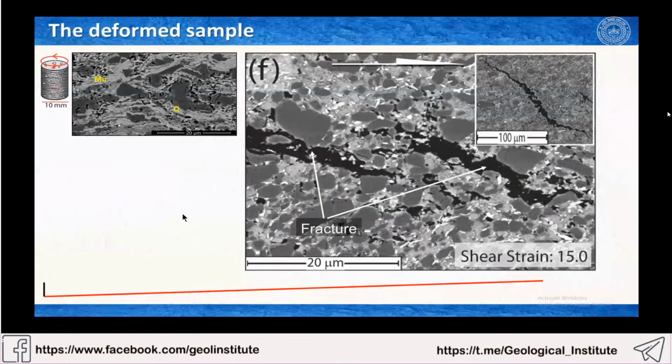And I remind you, everyone, that this happened again at 750 degrees centigrade. So at such a high temperature, you can produce fracture if the melts are gone from the system. Well, I did not drain them, but they got crystallized to produce some new crystals. So it became again dry. It doesn't have any melt, and it produced fracture at 750 degrees centigrade.